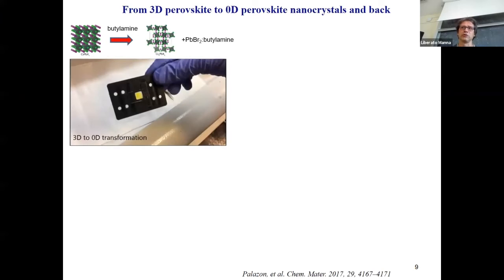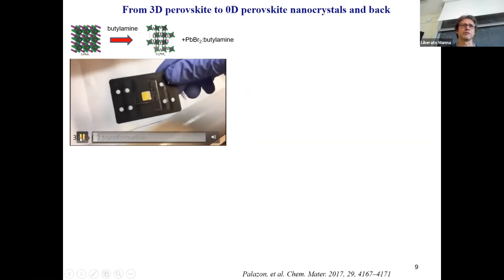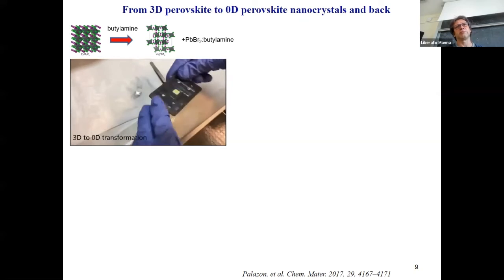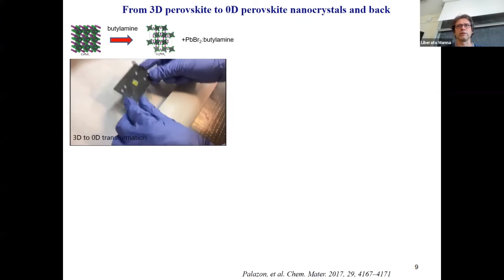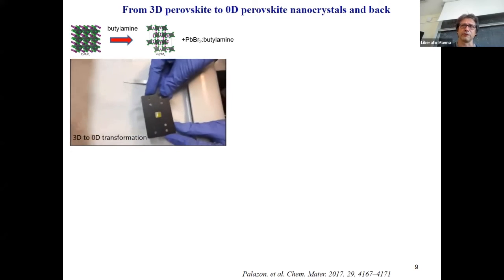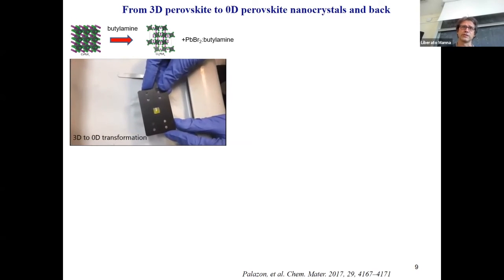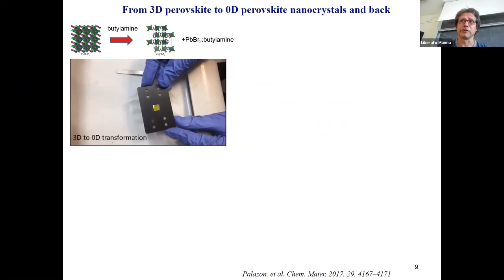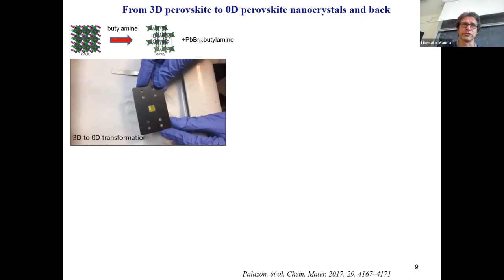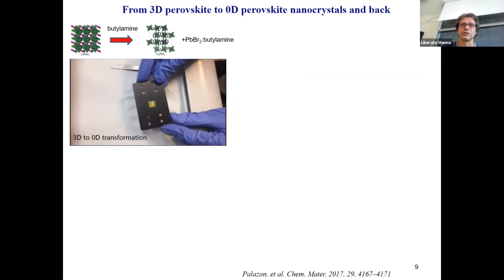You can also do very interesting reactions. So, for example, you can react 3D perovskites with an amine. This amine will basically form a complex with lead bromide, so we'll suck it out from the perovskite lattice, forming the 0D phase. And this is a reaction that occurs at basically room temperature.